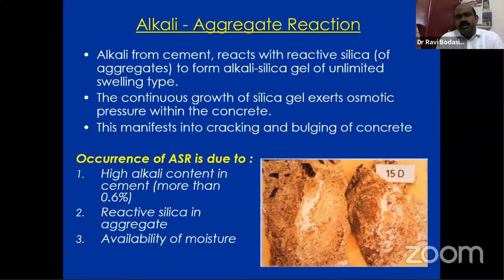So the next major effect is alkali aggregate reaction. The alkali content in cement reacts with the reactive silica of the aggregates we are using for manufacturing the concrete. Then a gel forms as both mix. Once this gel manifests, it causes bulging of the concrete and gives cracks. As you know, the crack is the first door that allows our structure to deteriorate at a faster rate.